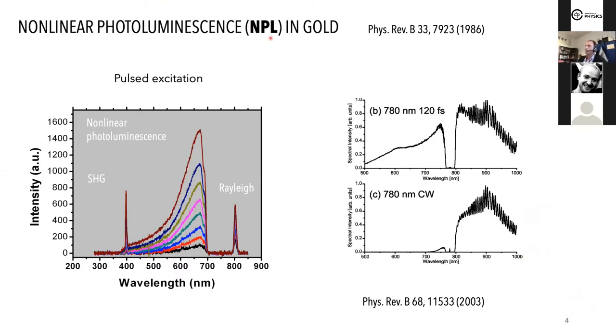Most of the time you will see in my slides this abbreviated as NPL, so nonlinear photoluminescence. You may find different acronyms in the literature, like TPL, which I'm going to come back to, which stands for two-photon luminescence, or TPPL, which would stand for two-photon photoluminescence. You will also find MPL, for multi-photon luminescence, and also avalanche photoluminescence. All these terms have been coined in the literature, but they're basically encompassing the same phenomena, which I better cast into this general term as nonlinear photoluminescence.